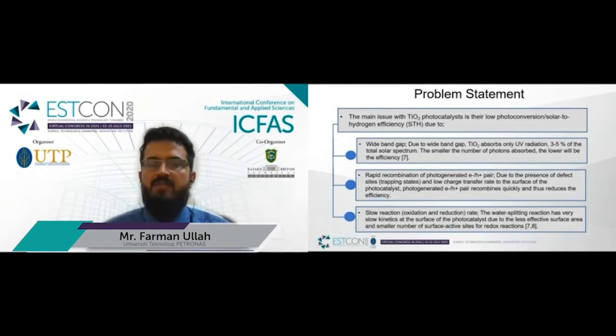The following are some of the problems with TiO2. First, the wide band gap, due to which it absorbs only ultraviolet radiation, which is just 3 to 5% of the total spectrum. So the smaller number of absorbed photons will result in lower efficiency. The second problem is rapid recombination of photogenerated electron-hole pairs, due to the presence of defect sites, which reduces the efficiency. Also, TiO2 has slow reaction rates. The water splitting reaction has very slow kinetics at the surface of the photocatalyst due to less effective surface area and a smaller number of surface active sites for the redox reaction.